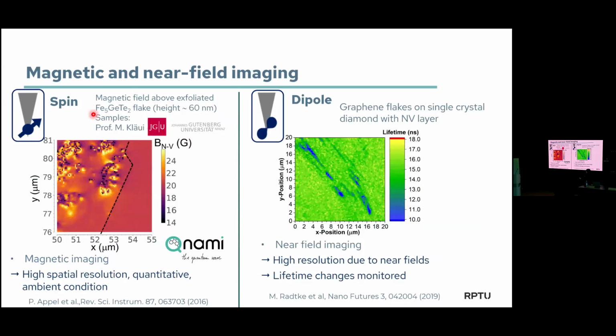And now we've come to the point that we have here a really tiny flake. I mean, you see here, the scale is just microns. And obviously we see a strong structure in the stray field of this flake. So that means it's a strongly multi-domain structure. And this is maybe to motivate for you why this NV magnetometry with the tip is interesting. So we can have, in principle, any magnetic sample. We can scan the NV over it. We can measure the stray field and then try to conclude back onto what's going on in the sample. And we can do this with a very good spatial resolution. So this is quite new results. This is why I chose it. I think that helps you to see that there's really a need for such measurements, especially also in material science.